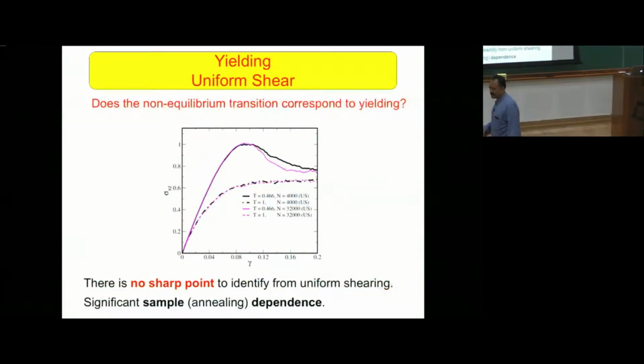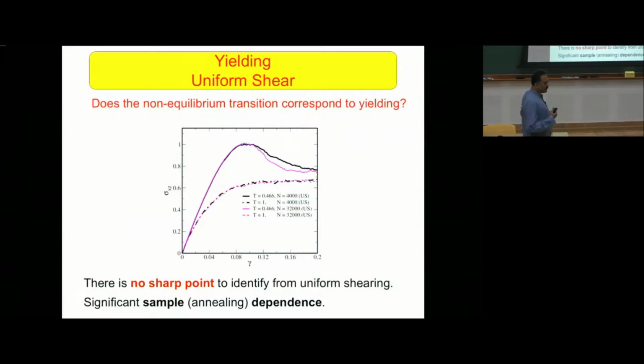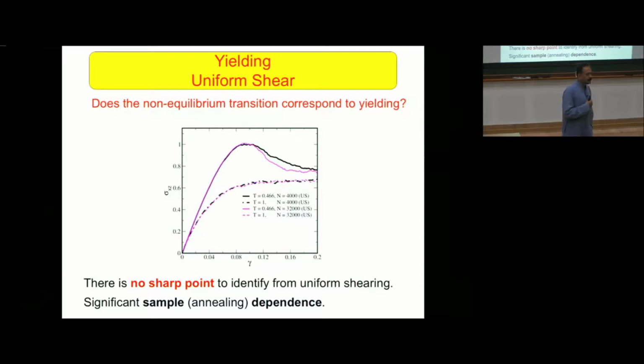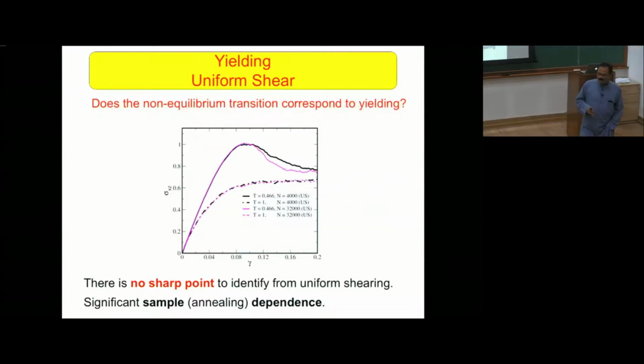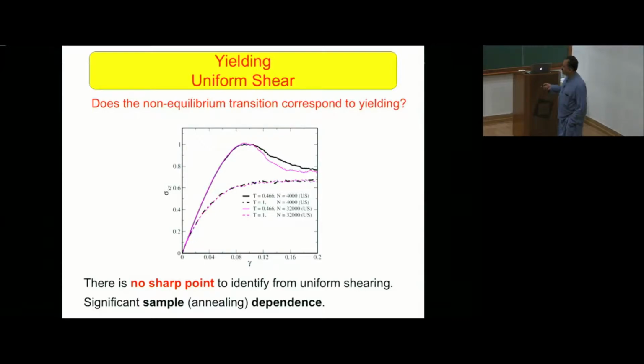Okay. The question is, does it help us understand yielding? And to motivate why this may be useful, I show the standard plot that people make in order to talk about yielding, which is a stress-strain plot. One thing that should be very obvious here is, if I was looking for a precise point at which yielding happens, there's no point I can pick out of this data, right? And it's particularly bad for poorly annealed glasses, where the stress increases gradually as I increase the strain. For well annealed glasses, there is an overshoot and there's a decrease. And so one special point you can pick is the peak of this curve. But you probably have good reasons to think that that's not where irreversibility started, right?